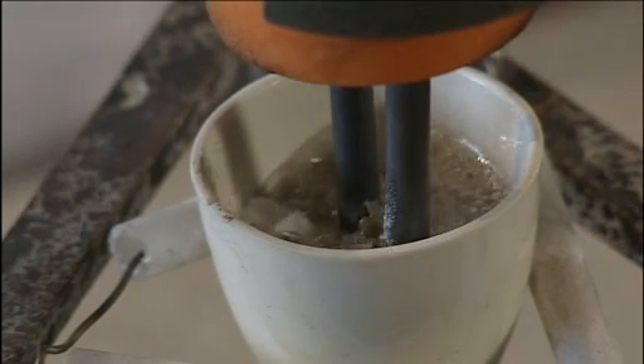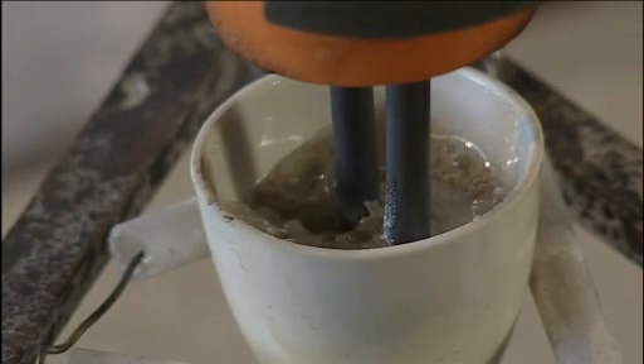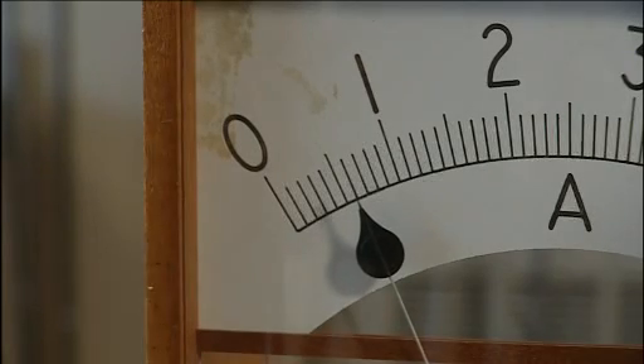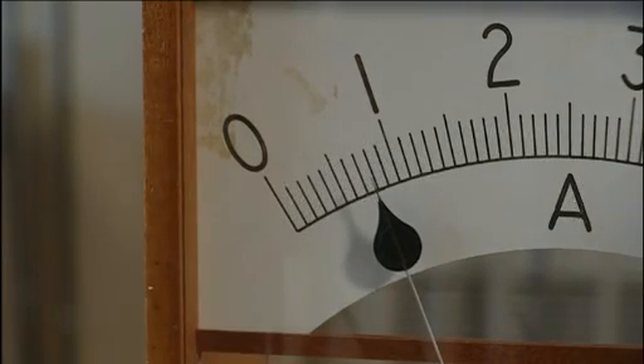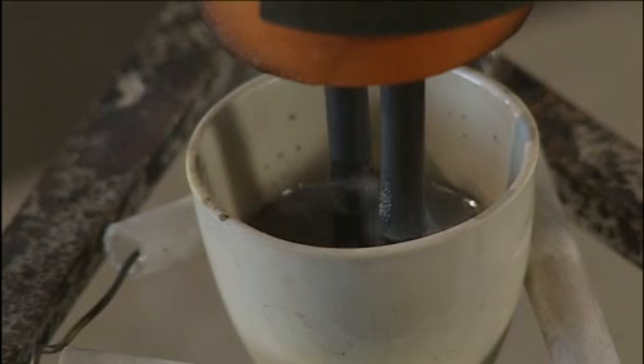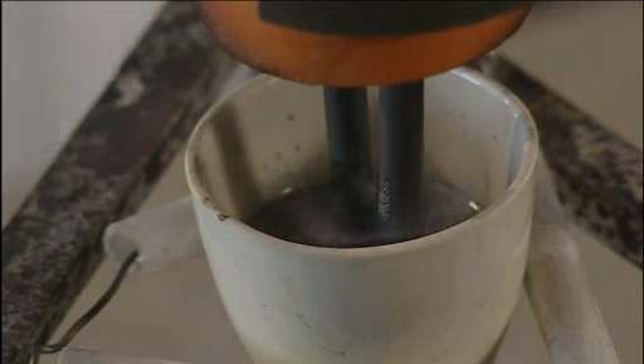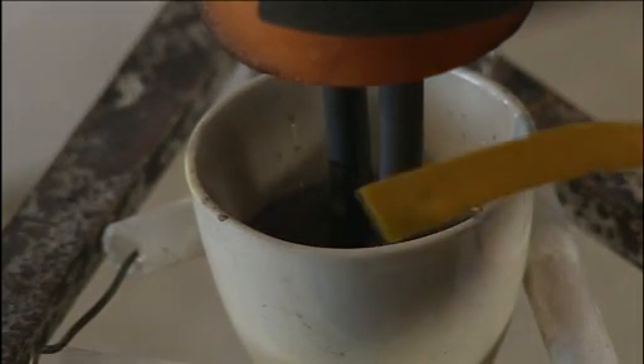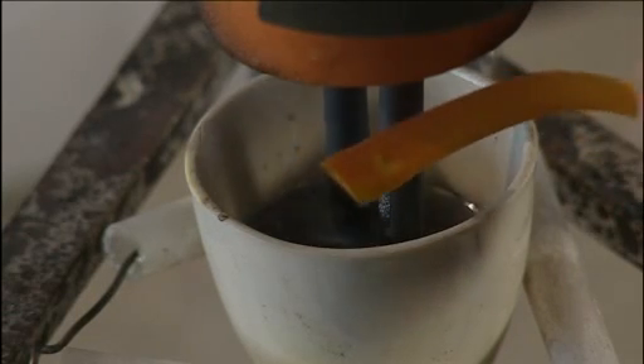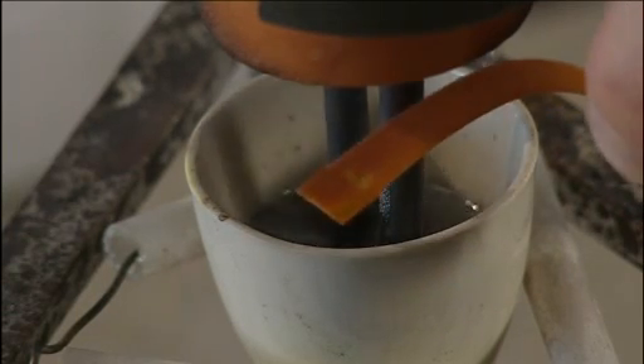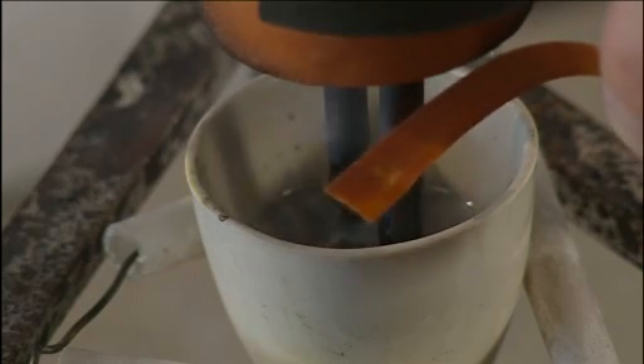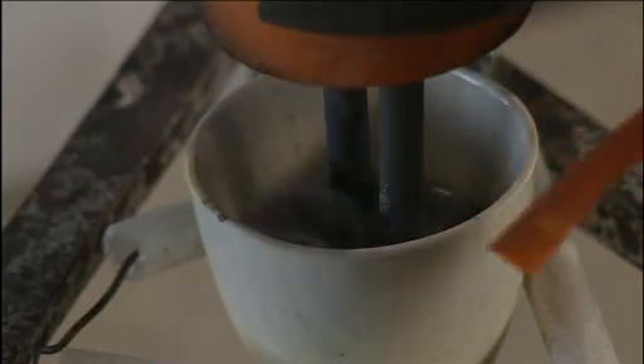As the zinc chloride melts, the ammeter will give a reading. Bubbles of chlorine will be seen at the positive electrode. We can test for chlorine using moist indicator paper, which goes red and then should bleach.